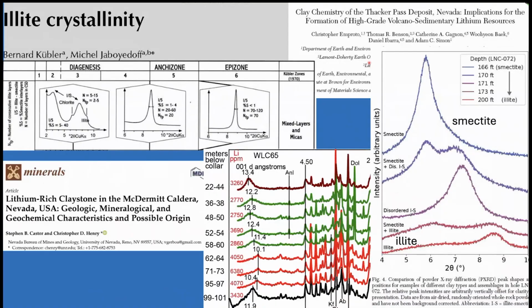Another method is illite crystallinity, and this looks at the shape of the illite peak on X-ray diffraction. And there's a plot by a guy named Kubler, and he's the namesake of the Kubler index, which is the illite crystallinity index. Basically it says that broad illite peaks like this are consistent with low temperature. Crystallization at higher temperature, the peaks become narrower, sharper, and at high temperature, they're very narrow, sharp.